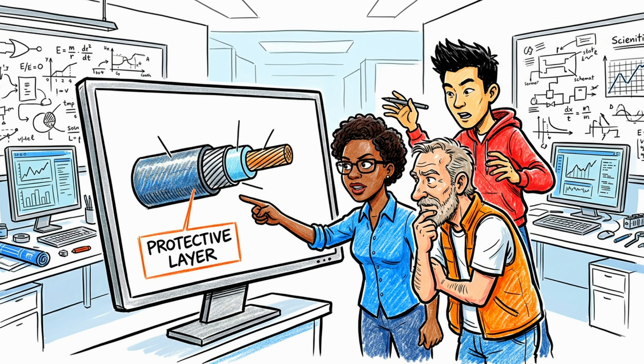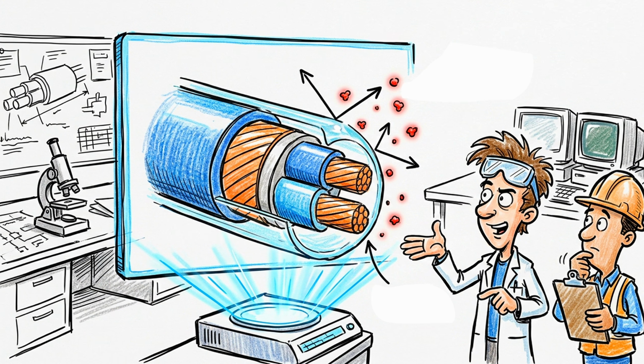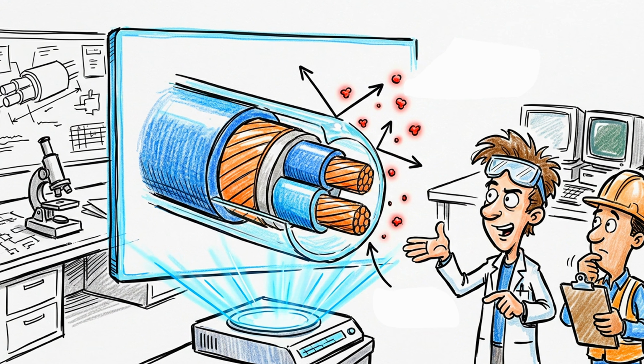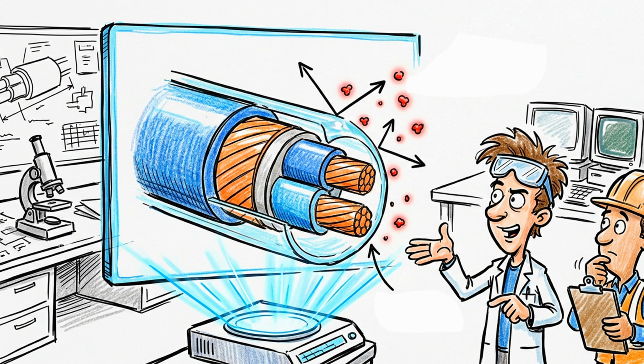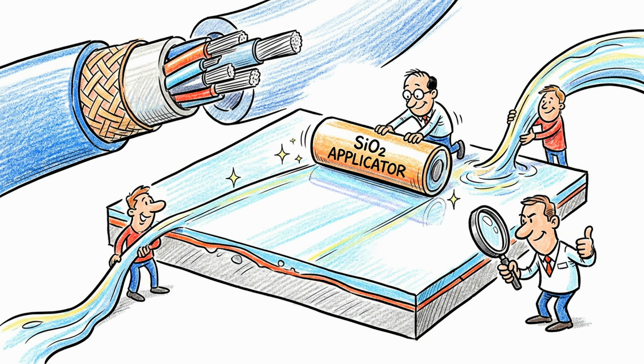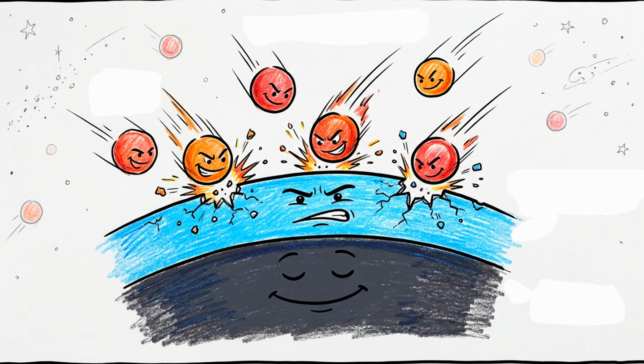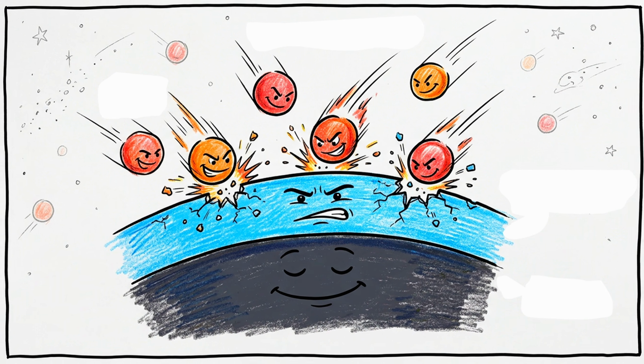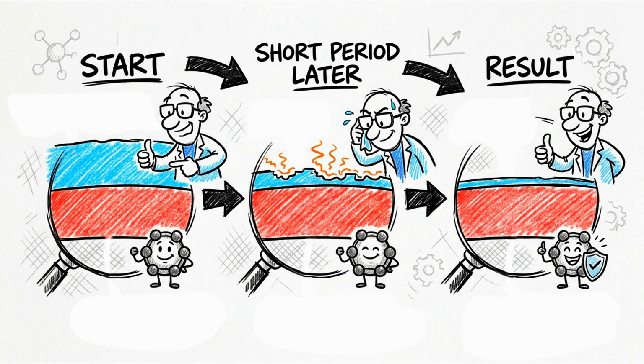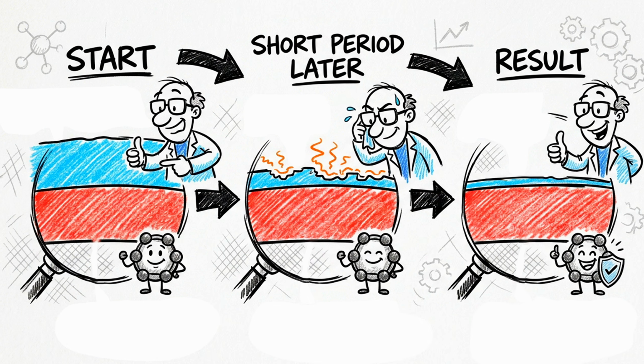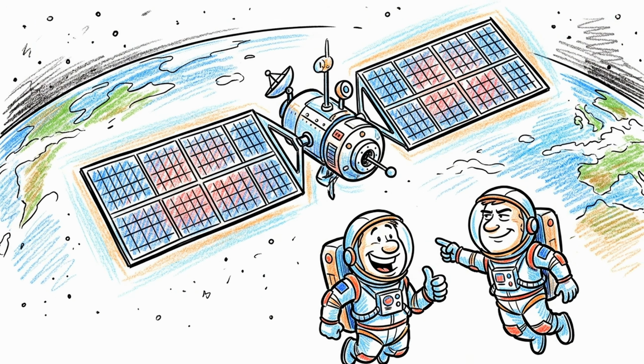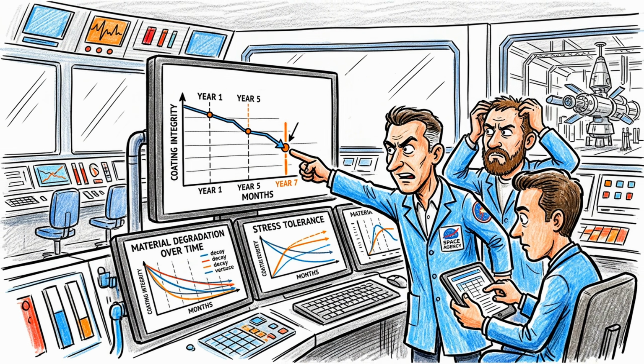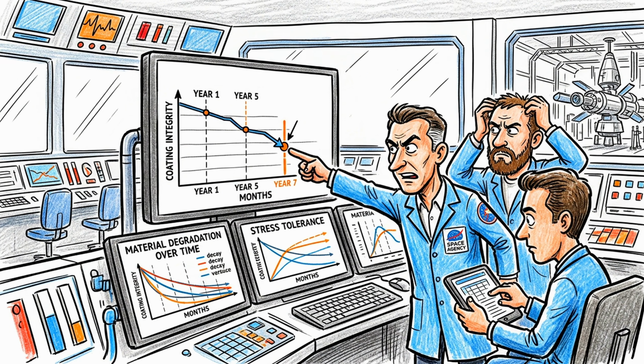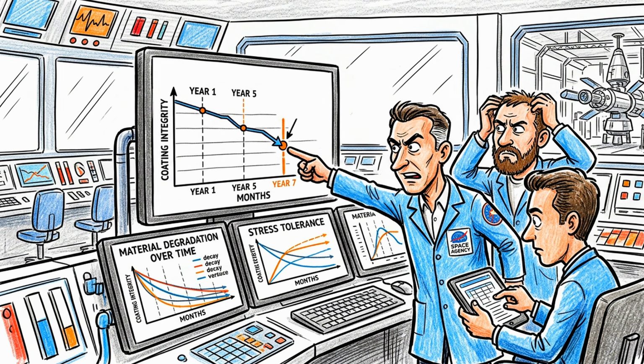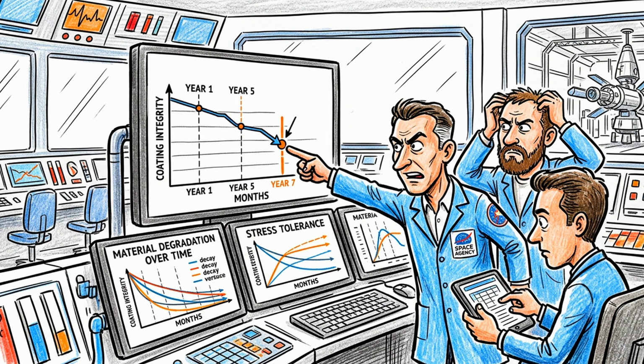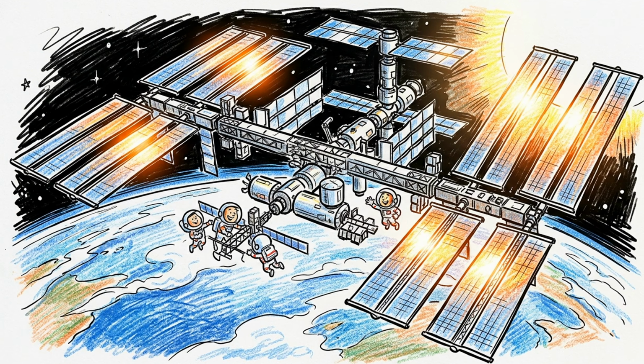The answer most engineers reach is a coating. Not the cable itself made of a different material, but the cable's surface protected by a thin layer of something that resists atomic oxygen better than carbon does. Silicon oxide works, aluminum oxide works. Both materials sit on the surface and allow atomic oxygen to oxidize them instead of the structural material beneath. The surface erodes, but it erodes slowly, and the carbon underneath is shielded. For a satellite panel or a station module, this works reasonably well. Engineers calculate the erosion rate of the coating, determine how many years it takes to wear through to the substrate, and schedule replacement or design for a finite lifetime. The strategy is operational. It is used right now on structures in orbit.